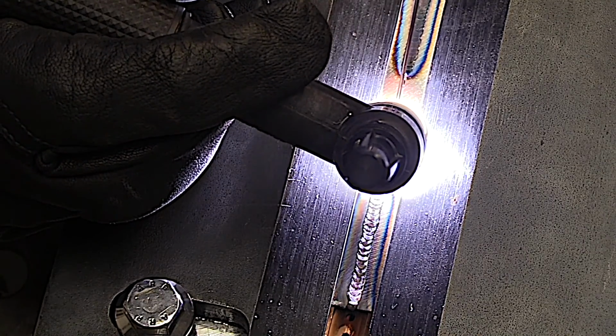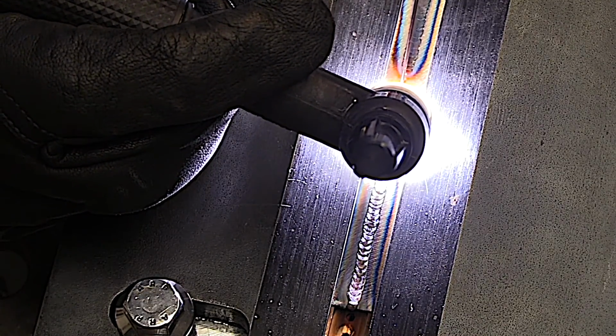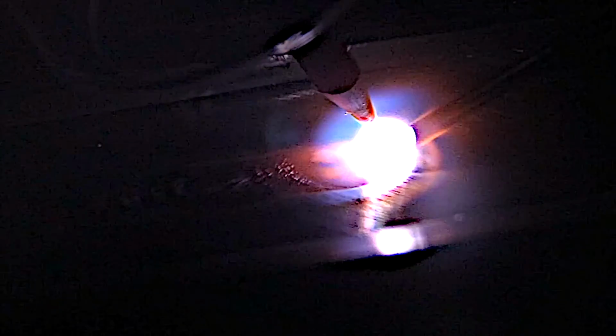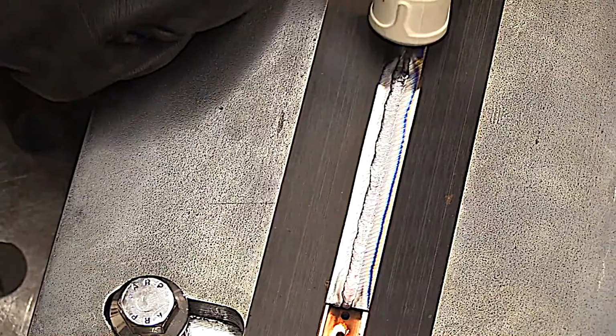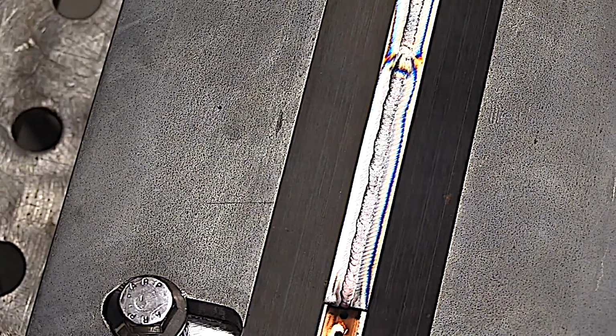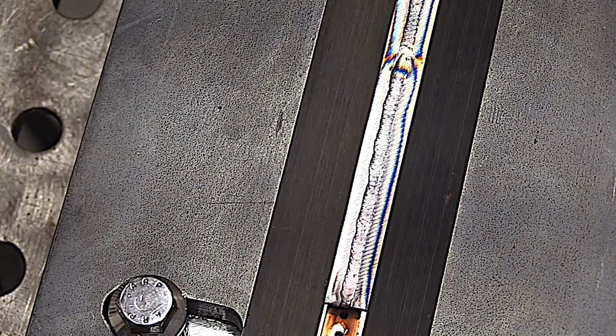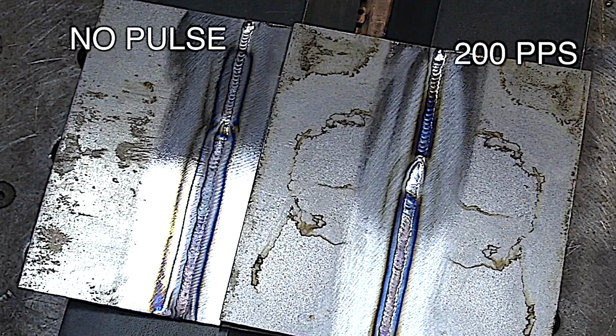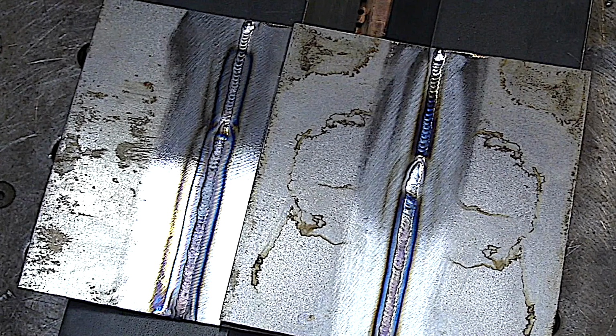We're going to come up on that previous weld. Just the same old fundamentals. We're trying to keep a tight arc, move along at a consistent rate, keep the hot tip of the filler shielded by the argon. And as we move into that previous weld, quit adding filler, keep moving forward, taper off the amperage to 0, and that's what prevents a crater crack, especially on crack-sensitive alloys like chromoly, precipitation hardening stainless, Inconel 718, etc. There's the no pulse, there's the 200 pulses a second. Definitely a little bit of difference, not like night and day.